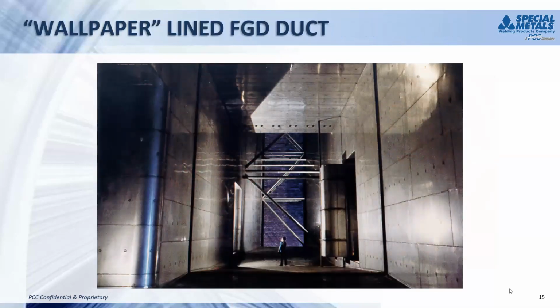The next slide shows an outlet duct that was lined with alloy sheet by the wallpaper technique. This is alloy 22, 1.6 millimeter sheets. They're about 48 inches wide and about 120 inches long. And they were attached to the steel structure to protect the material from the aggressive environment inside the duct. You can see some plug welds in the center of the plates that are used to reinforce the attachment of the sheets to the steel structure.